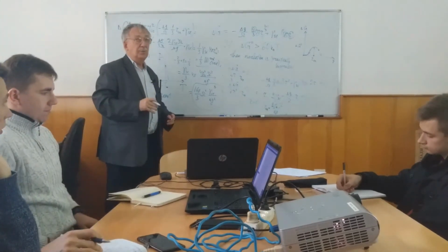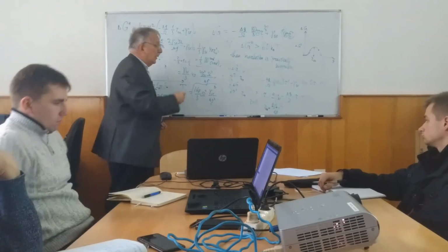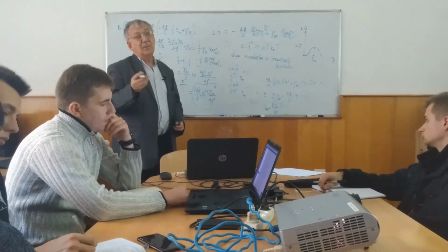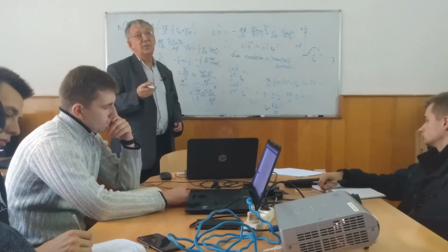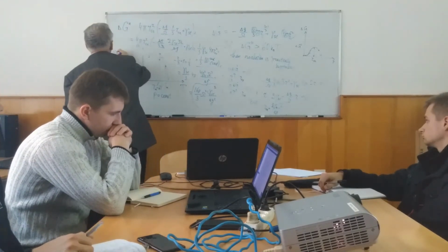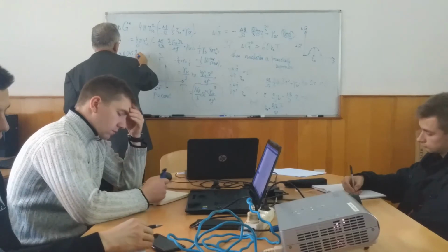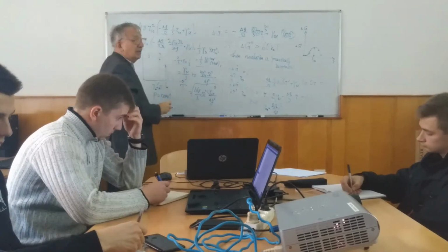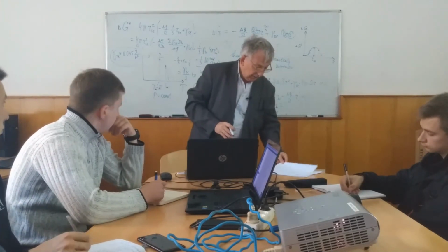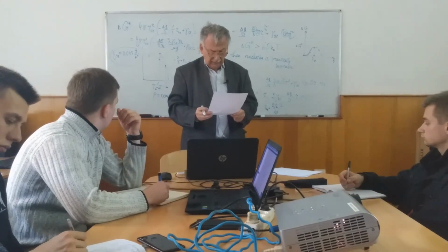Now, it's not the end of the story, because I said that we should make some estimations, and we'll make them. We can estimate some gamma. Since my work is related somehow, and your work, by the way, also is related somehow to tin solders, I can say that gamma SL for tin is about 0.45 joules per meter squared. So this is gamma. Just write it down. It's an estimation. I will check. I wrote somewhere, but I forget where I wrote this number, but I remember it.